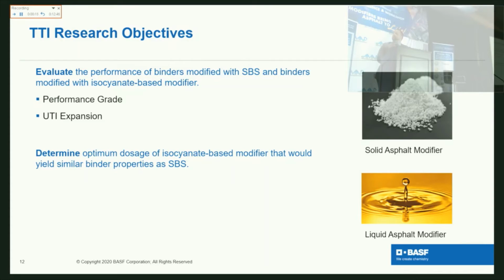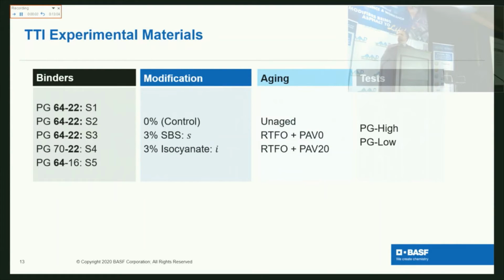Okay. The other task that was set to them was to determine the optimum dosage of isocyanate-based modifiers. So essentially we wanted to yield similar properties to SBS as much as could be done. So they took, again, the 5 different asphalts, some from the Midwest, some from down south, some from out west. We had a 0% control, then a 3% SBS, 3% isocyanate, and they just basically ran it through the normal slew of performance grade testing.